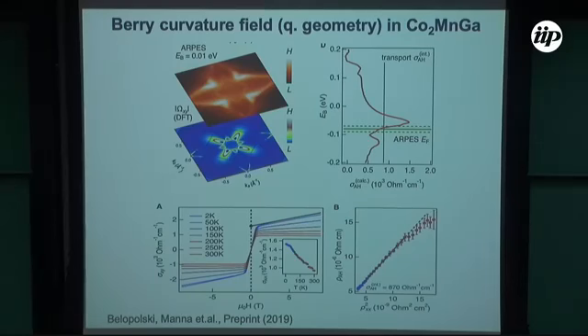The reason I show this is that spectroscopy has advanced to a point that we can take all these relevant parameters and predict transport, not just image topological order and topological invariants. In the historical sequence, people would do some transport and then try to do some spectroscopy to figure out the microscopics, what is happening in the system, why transport is the way it is. Here we are now reversing the direction: spectroscopy has advanced so much that we can predict certain types of transport. This is not just one example. We have more examples.